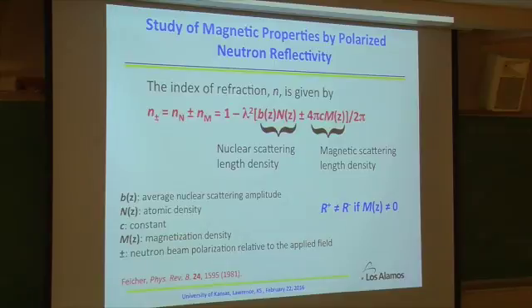What we did is we use neutron diffraction measurement. So here we use polarized neutron reflectivity. That's probably, as a physics department, the only formula I'm putting over here in physics. If you look at the index of refraction, that's also related to the nuclear scattering length density or magnetic scattering length density, right? It basically depends on the neutron spin up, spin down. That's why there's a plus minus sign over here. If that's a magnetization over there, then the plus minus should not equal each other. So that's basically the physics over there, okay?